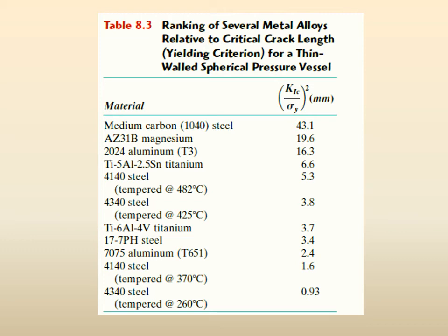The whole approach is that I take my critical stress as sigma y divided by a factor of safety, because it is yield before fail. And then using this criterion, I compare the AC, the critical crack size, for each one of them, and that is it. So the approach is okay even for 1 material, 2 materials, but unless you apply it to all, say, the 20 materials in the table, you don't know which one will give the maximum value. But that is it, right?